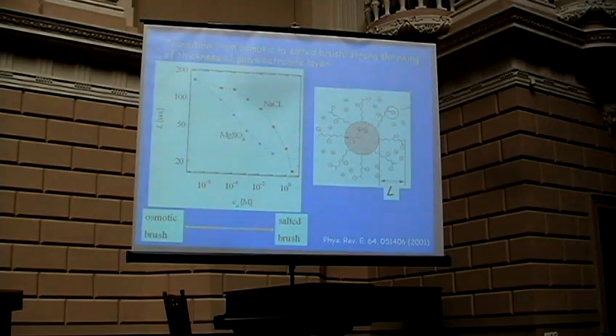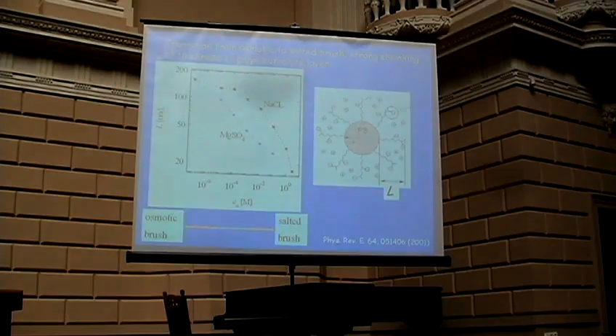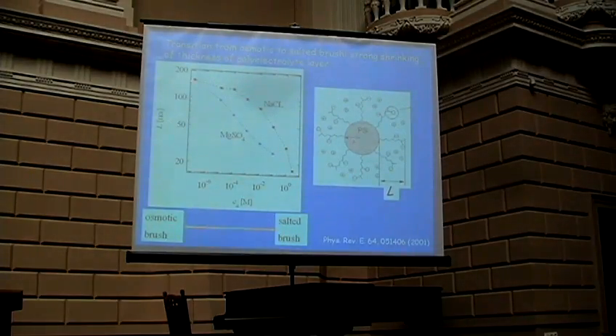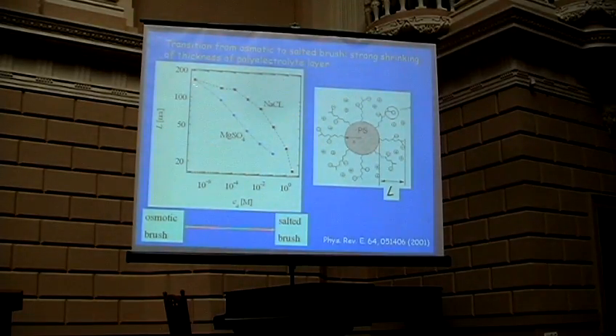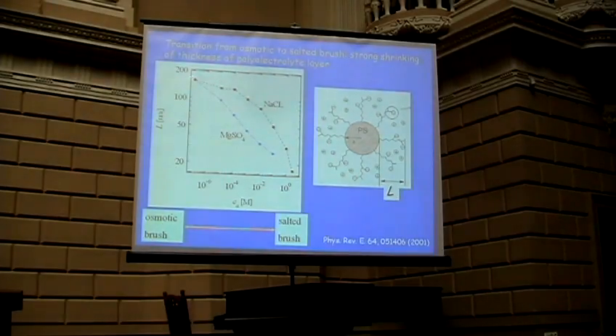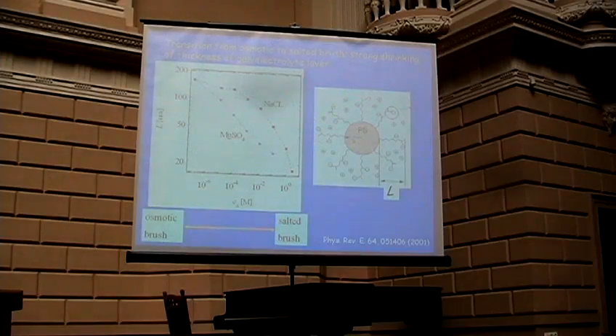A very important point is what is the length of the surface layer. You can even see it from the picture, but you can measure it by dynamic light scattering very precisely. Here, in this case, the full length was something like 200-something nanometers, and you see the stretching is nearly 180 nanometers in the salt-free solution. Now, if you add salt, the length becomes shorter and shorter. You go from the stretched to the coil state of the polymers, as you expect. Because if you add more and more salt, you are screening the Coulombic potential. Then, after all, at high salt concentration, you have essentially an uncharged system, so you will come back to the uncharged system. What we discovered here: if you took magnesium sulfate, the collapse of the chains was much more pronounced. At this point, the data stopped, not because the solution was turbid, but because the particles precipitate.